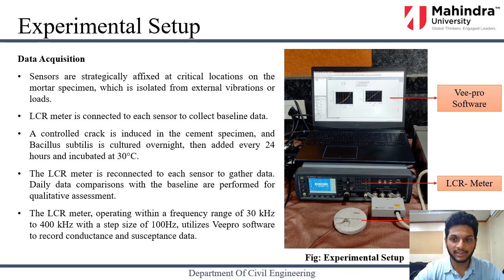Coming to the experimental setup, we use vPro software and an LCR meter to get our signatures from the test specimens, and the sensors are strategically fixed in critical locations very near to the crack of the mortar specimen. The operating frequency of the LCR meter which we used was from 30 kilohertz to 400 kilohertz with a step size of 100 hertz, and we added the bacteria every 24 hours and incubated the specimens at 30 degrees centigrade.